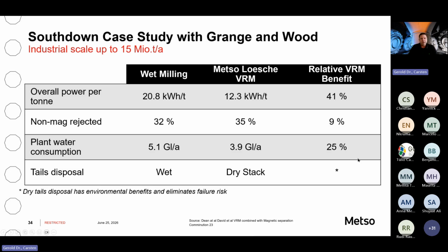Comparing now the final data of the solution that the Metso-Loesche VRM provides in comparison to the wet milling, which was a wet SABC circuit, which resulted in 20.8 kilowatt hours per ton, we had a 41% saving of energy. We could increase the gangue material that was rejected by 9%, and the plant water consumption could be reduced from 5.1 gigaliters to 3.9 gigaliters, which is 25%. But one of the biggest issues, like I just said, is to be able to change from wet to dry stacking. The saving in energy equals 127,500 megawatt hours per year. In water, it's 1.2 gigaliters per year.